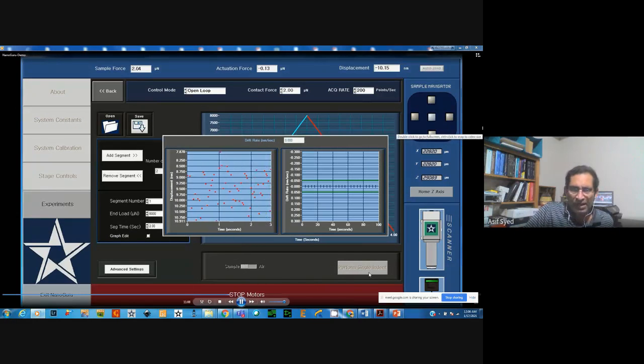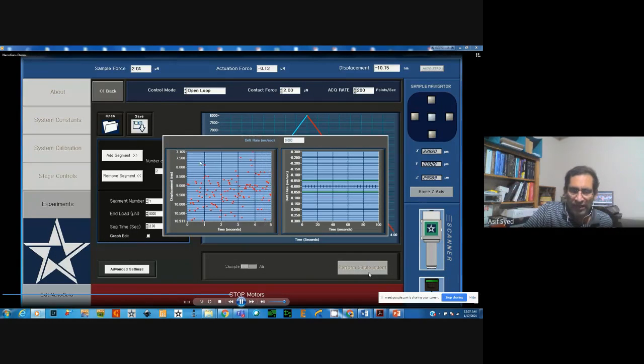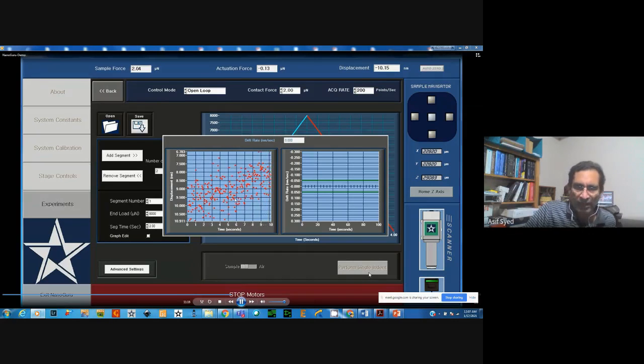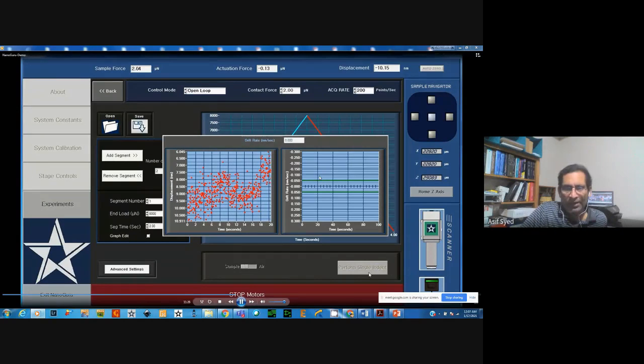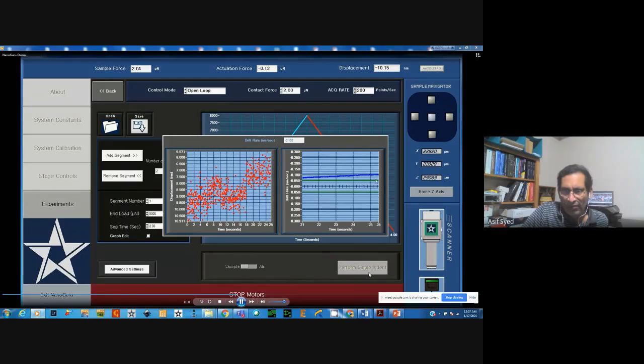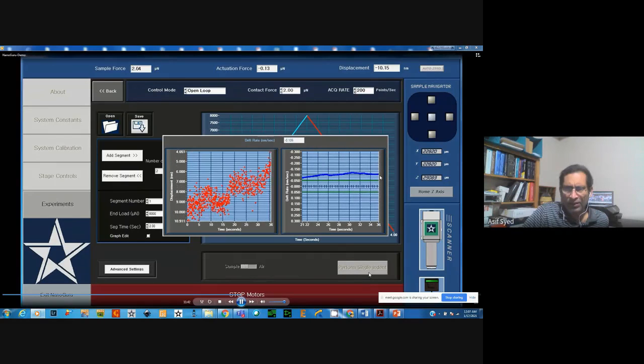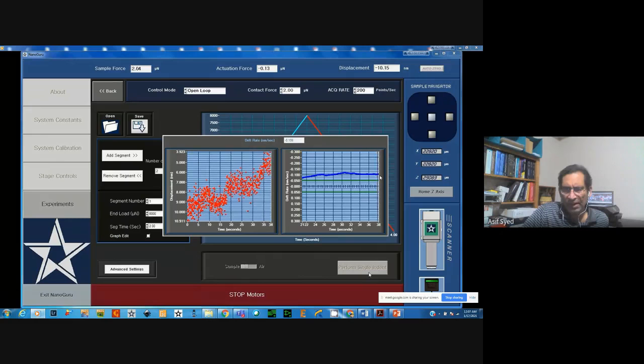So what you see is basically a window where it is measuring the displacement as a function of time. From the displacement as a function of time reading, it measures the drift. So when the drift reaches a certain number, for example 0.05 in our case, sometimes maybe higher depending upon the room condition, it will immediately start doing the experiment. Here at least now it is about 0.075 or about 0.1 nanometers per second. So when it reaches the parameter that we set as the drift, it will start automatically doing the indent. Okay, just give me a second now.